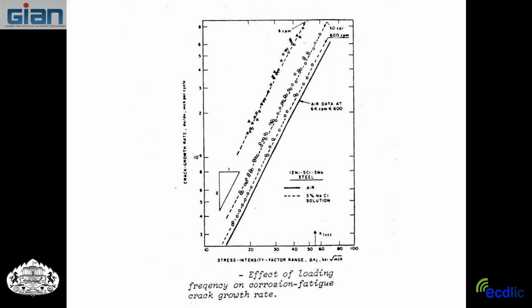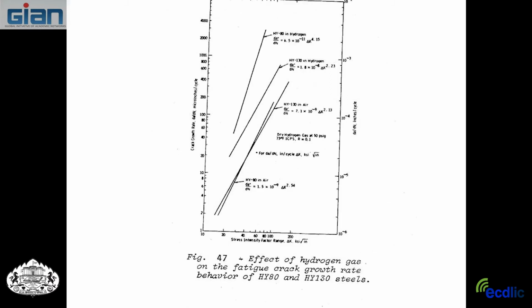If you do a fast frequency, you're up and down, and you don't spend much time in any one cycle in that bad range. If you have a slow frequency, you're up there for quite a while. So at 6 cycles per minute, you're up there 10 seconds, then 10 seconds in that range, and then you get that big effect.